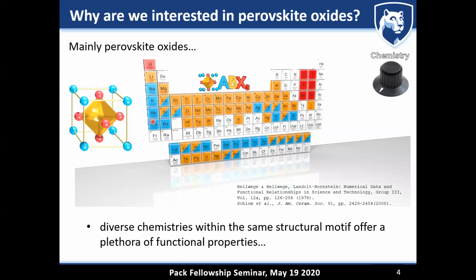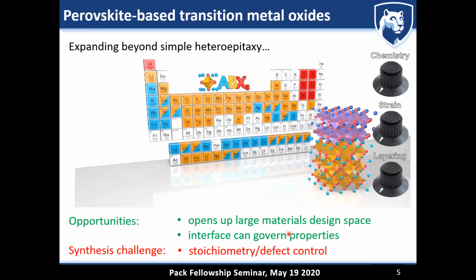Now the interesting thing is that if you are able to grow these materials by a thin film growth technique, there are a few more design knobs that you have access to, which you typically don't have if you grow bulk materials. The 2 things that we have are that we can strain those films and change the properties that way, but we can also start to use the layering scheme as a design parameter to change the functional properties in these materials. Now, these 2 opportunities come with a challenge.